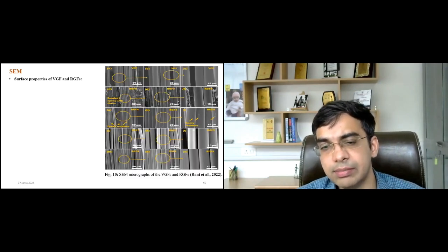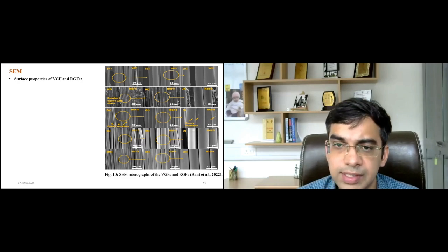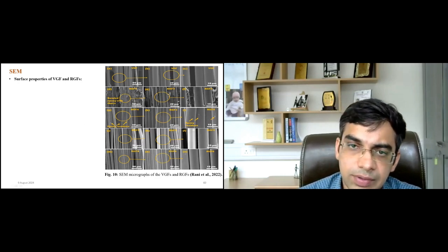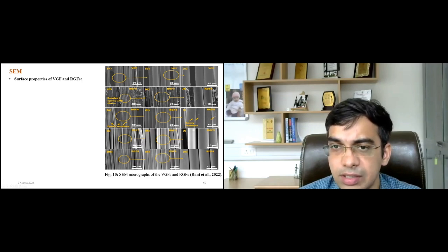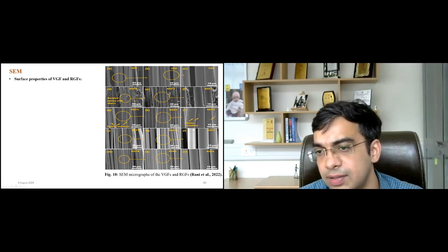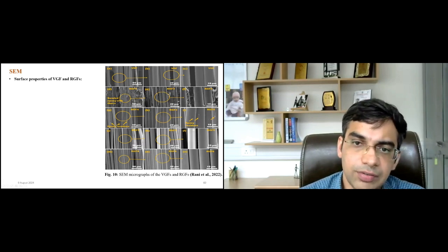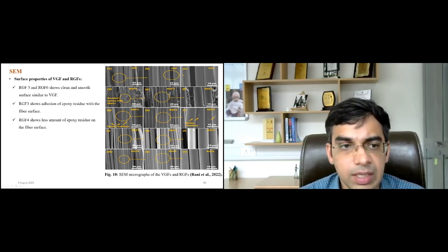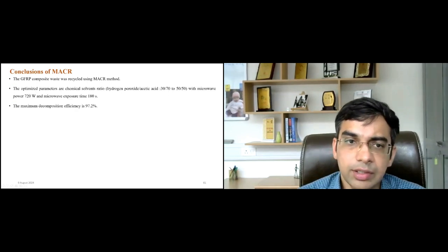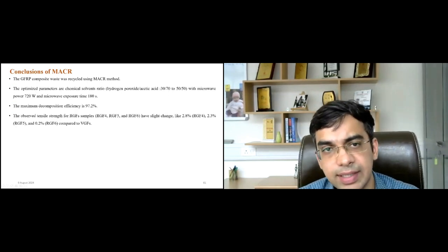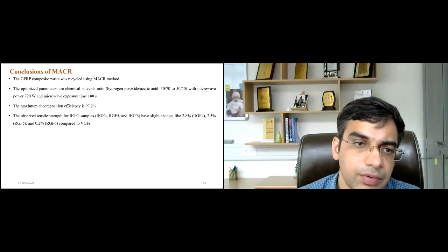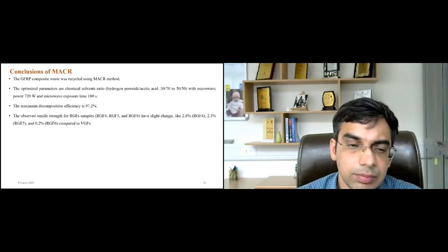We also conducted scanning electron microscopy on the recycled fibers. At unoptimized conditions, we observed that epoxy is still present on the surface of the fibers, but at optimized conditions, like RGF 5 and 6, almost clean fibers with no damage were recycled back from the process of microwave assisted chemical recycling. So what I can conclude is that microwave assisted chemical recycling is starting a new paradigm in recycling fiber reinforced plastics, and with all these attributes, it could be one of the promising processes in coming time.